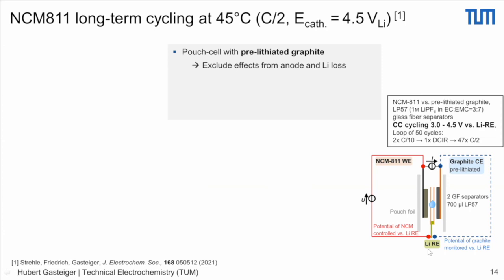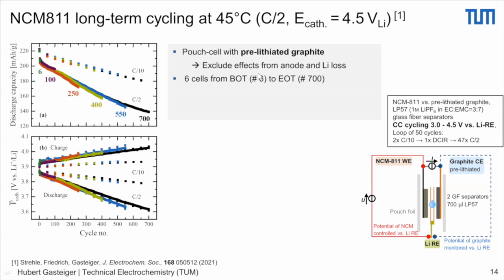And the approach for this: we set up a study where we looked at the long-term cycling stability of NCM 811 at 45 degrees. The C rate was C/2 at a cathode potential of 4.5 volts. This is, of course, a rather high cathode potential, so it was supposed to be an accelerated study. We used pouch cells with a lithium reference electrode, where the graphite electrode was pre-lithiated to avoid any contribution from active lithium loss, and where the working electrode, the NCM 811 electrode, was cycled against the potential of the reference electrode. We had six cells in this case, which we cycled to different cutoff cycle numbers: 1, 100, 250, 400, 550, and 700.